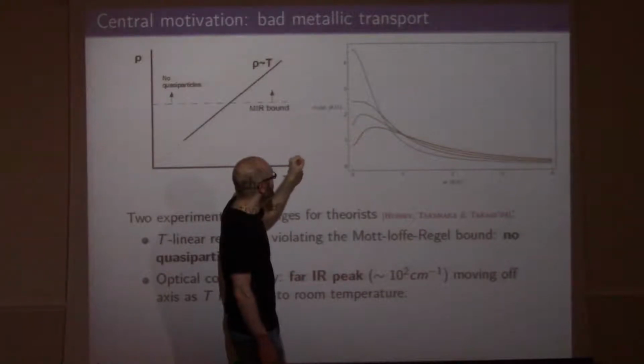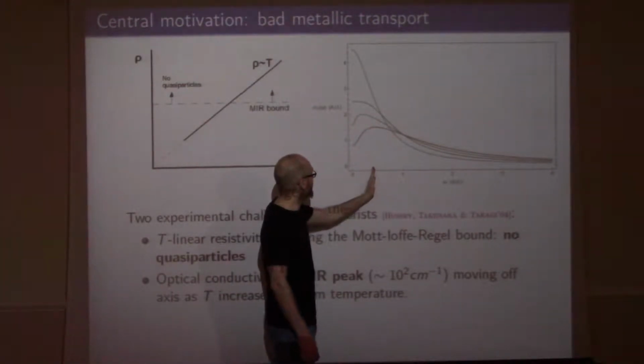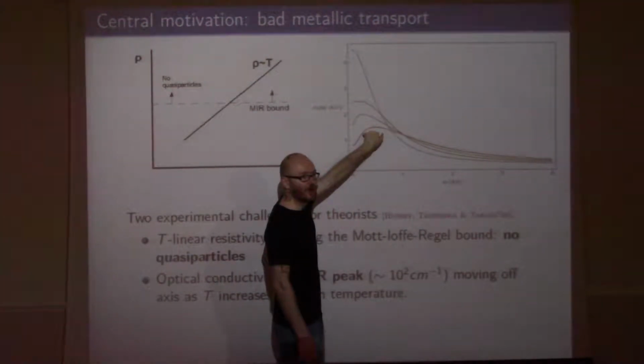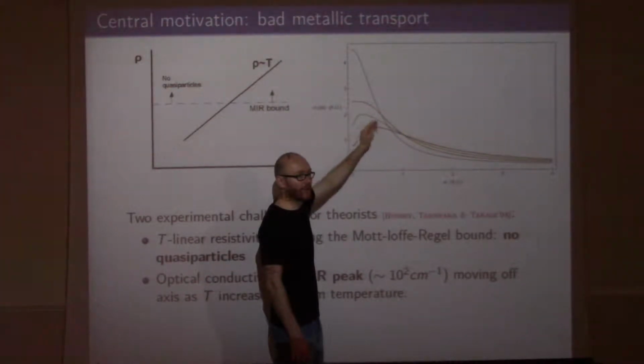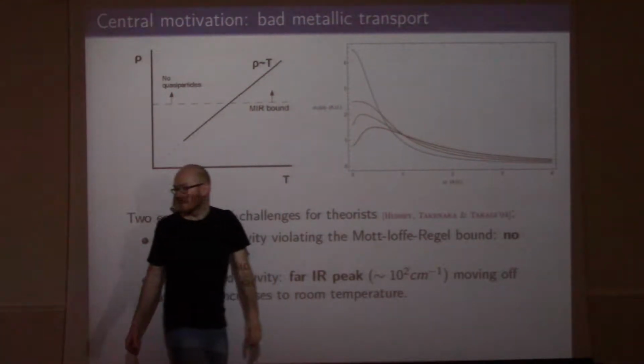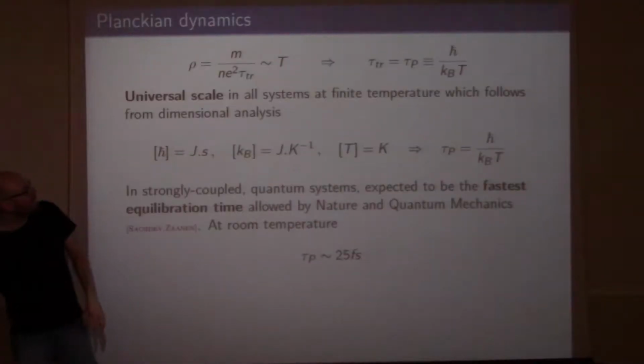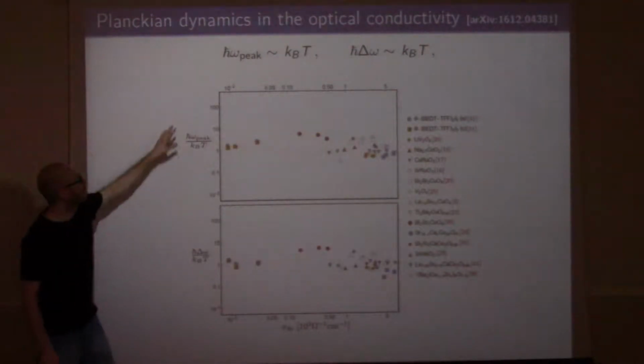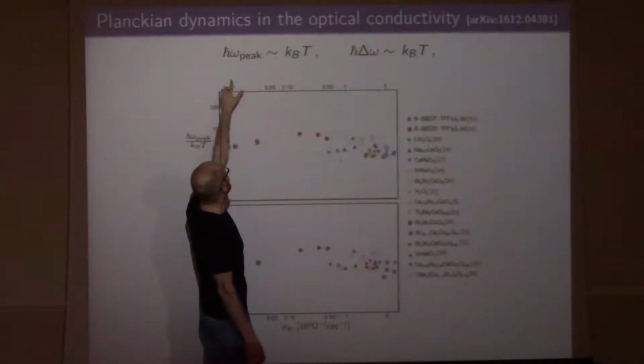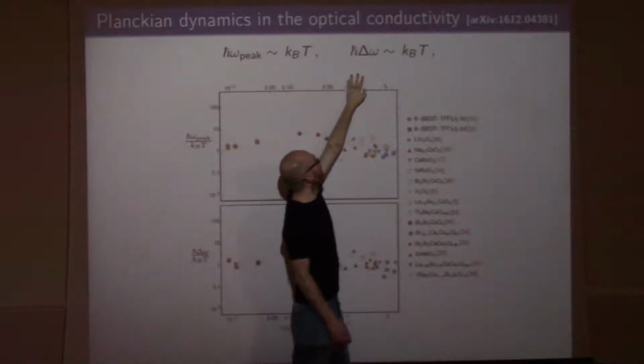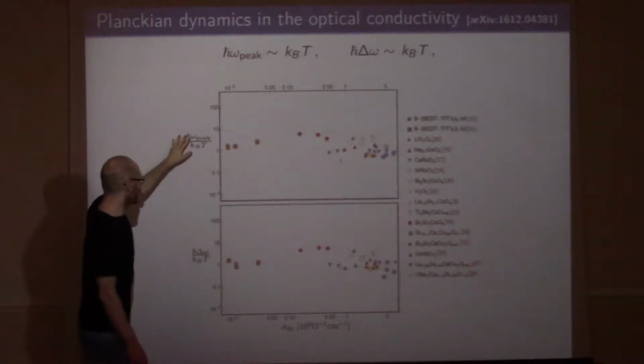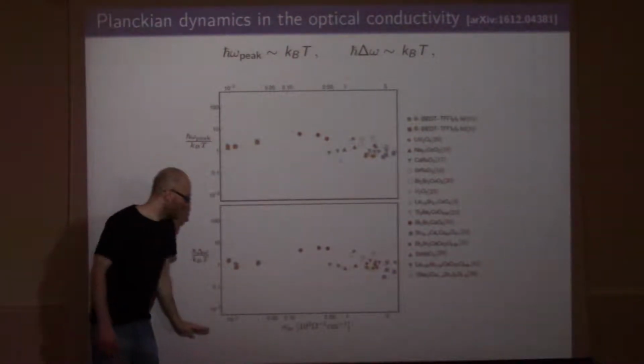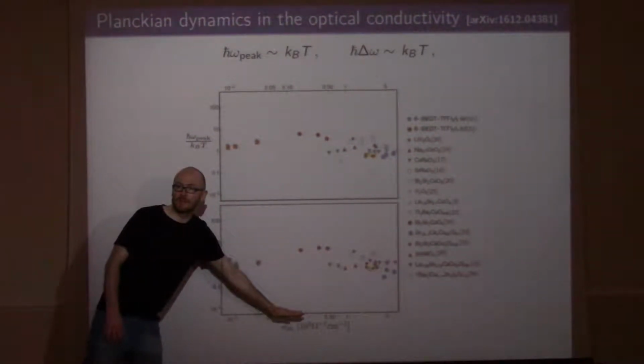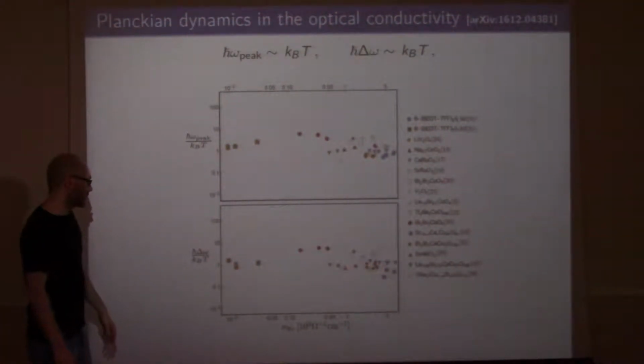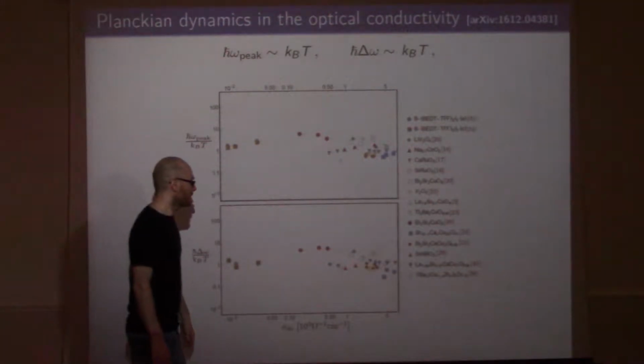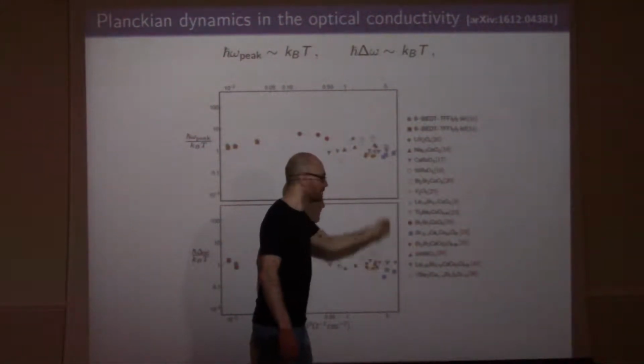So then what you can do is catalog the position of these peaks and the width of the peaks along the frequency axis, and then you plot them versus h bar over kBT. This is what I'm doing here. I have the position of the peak and the width of the peak, and I'm plotting them versus temperature, and I'm scaling them using the DC conductivity. So this MIR bound would be somewhere here, roughly speaking.